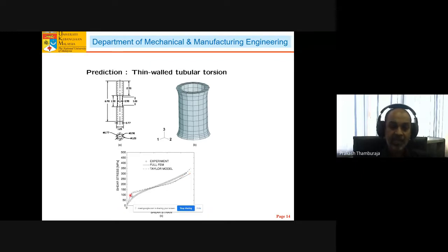So you can clearly see that the computational simulations are actually able to predict the experimental response to quite accurate accord, given the complexity of the deformation mechanisms and the microstructure in the material. So it also gets captured by the constitutive model, and the homogenized model as well is able to predict the stress strain curve to good accord, albeit with slightly premature locking, but still the overall response is quite good as well. So we are doing quite well in a multi-axial loading state. So let's make things more interesting now.